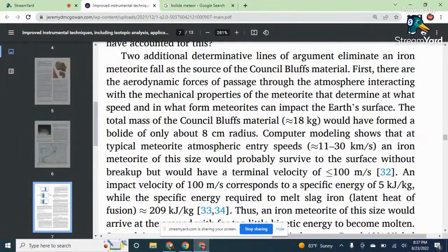So let's see, where were we? Okay, the total mass of the Council Bluffs material, approximately 18 kilograms, would have formed a bolide of only about 8 centimeters radius. So 8 centimeters is not that big. Computer modeling shows that at typical meteorite atmospheric entry speeds, approximately 11 to 30 kilometers per second, an iron meteorite of this size would probably survive on the surface without breakup, but it would have a terminal velocity of,